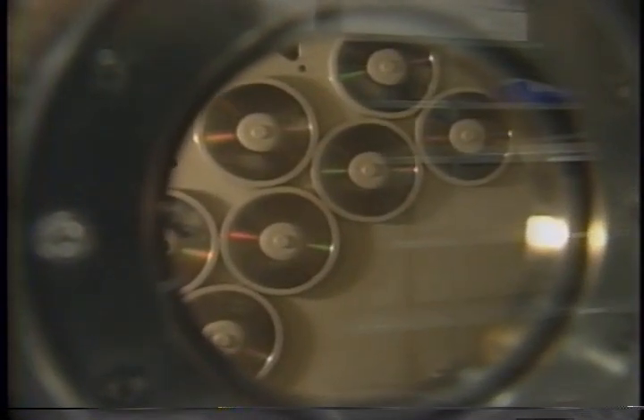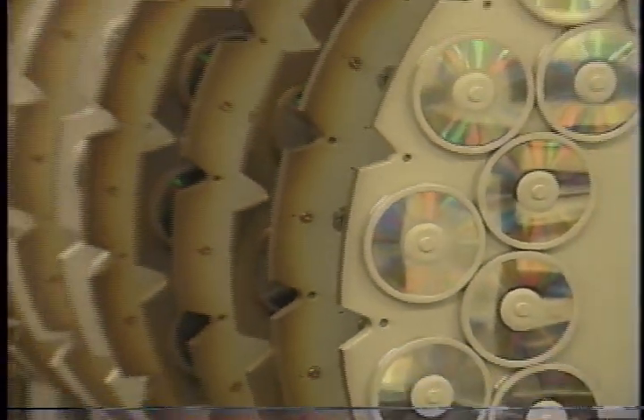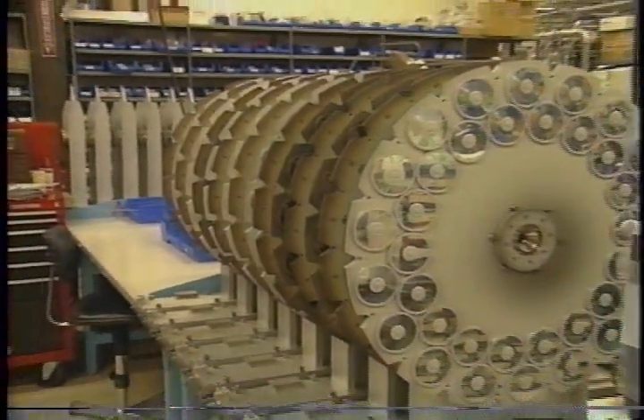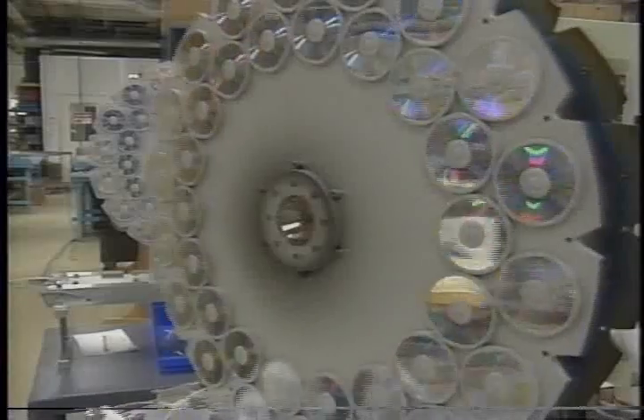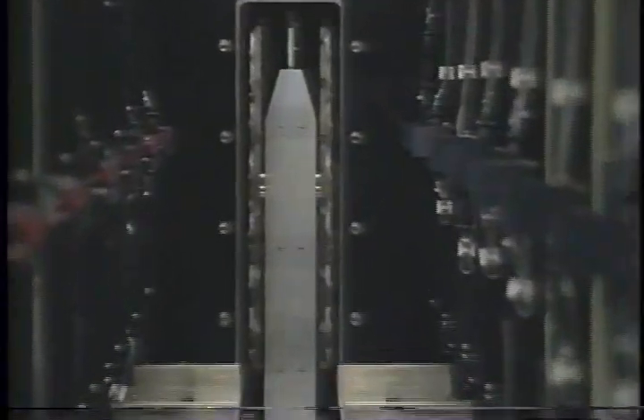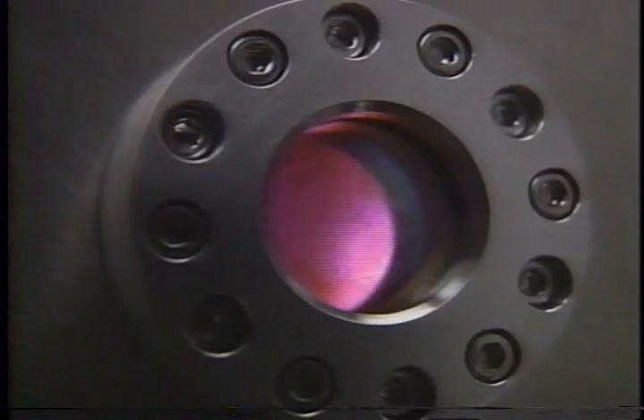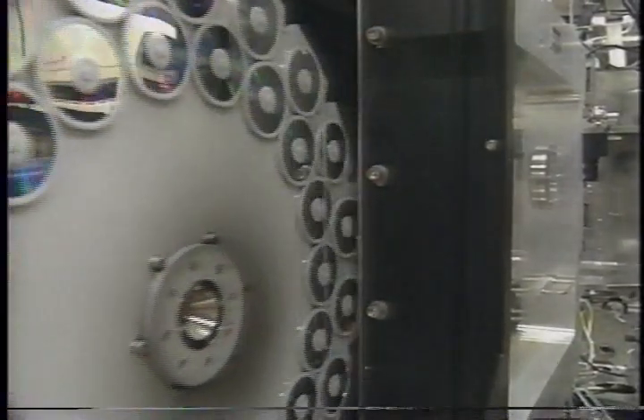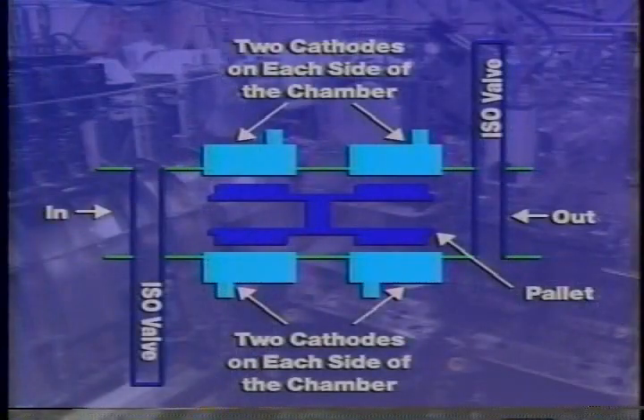If you're wondering about productivity, the inline sputtering system is designed to coat more mini-discs faster than any existing alternative. You're looking at the world's highest throughput. It begins with the system's double-sided design, which holds 44 discs on each pallet and 2 pallets to the carrier. Quite simply, double-sided coating means double the output. It continues with DC reactive sputtering, which is 3 to 10 times faster than conventional RF processes. And it extends to the inclusion of as many as 4 cathodes per process chamber for even faster work.